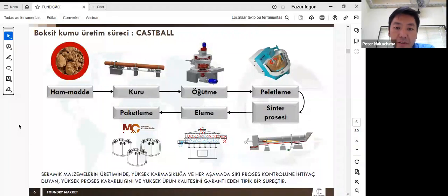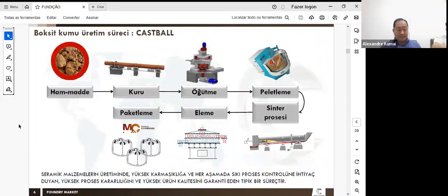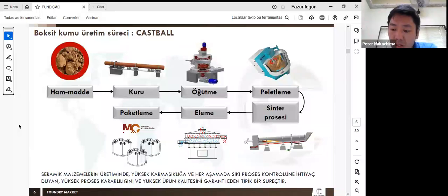After sintering, we have the sieving process that defines the final size distribution of the Castball by using a vibratory set of sieves with different openings to reach the adequate GFN and the adequate size distribution of the product. And after that, we have the packing. During packing, our quality control is responsible for collecting samples from each big bag and run all the analysis for the Castball. For instance, size distribution, GFN, density, pH, ADV, and tensile strength.